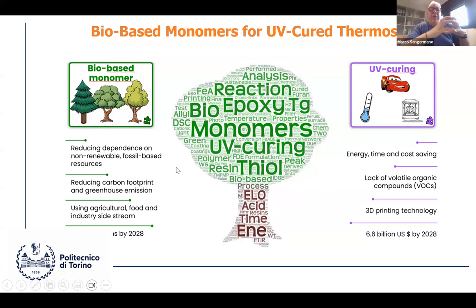The reaction starts from a precursor, a monomer, which is reacted to form the polymer, the cross-linked polymer in the case of UV curing. Usually the monomer comes from fossil derivatives, so it comes from petroleum. If we start from bio-based monomers, we have an important sustainability, because we have the sustainability of the material and the sustainability of the process. So starting from bio-based monomers, we reduce the dependence on non-renewable fossil-based resources, we reduce the carbon footprint, as I mentioned before, and we can use agricultural and food industry side streams as sources for the polymeric precursors.